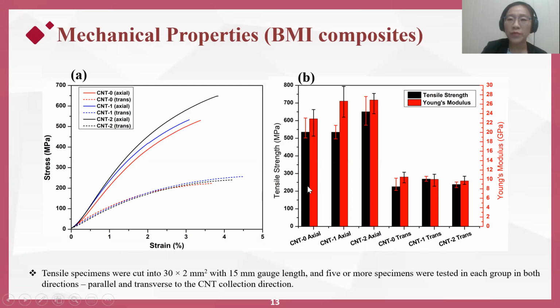Along the alignment direction, the CNT0 and CNT1 composites demonstrate similar tensile strengths of about 535 megapascal, shown in black here. A 21% increment in tensile strength was observed for the CNT2 composites. The Young's modulus of the water-assisted group was about 27 gigapascal, which is about 16% higher than that of the control group. The improved mechanical properties could possibly be attributed to the decreased number of CNT walls and smaller diameters. Additionally, less amorphous carbon with the water cleaning effects may have enhanced the interface.